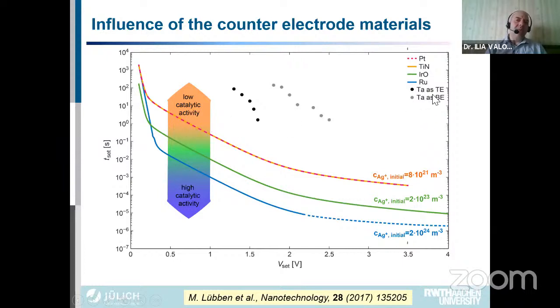And if you take, for example, materials which oxidize and provide an even higher resistance barrier, like tantalum, which can oxidize, you see that the results are much slower. The switching kinetics is much slower compared to, in that case, ruthenium, which is given for comparison, by orders of magnitude. So changing different electrode materials allows us to change the reaction rate and also the device operation time by orders of magnitude, not only a few, it's really by orders of magnitude.